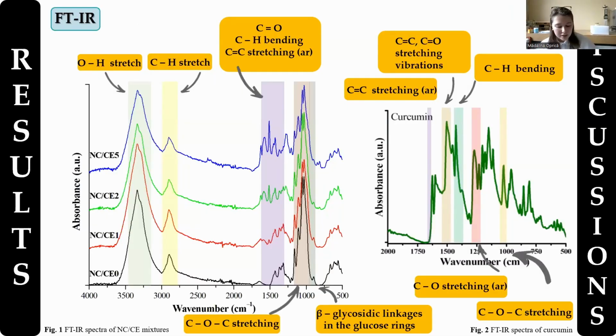The FTIR spectra presents the characteristic bands of nanocellulose, with the most important peaks at around 3,340 attributed to the hydroxyl groups abundant on the nanocellulosic surface, another at 2900 centimeters at -1 attributed to the carbon-hydrogen stretching vibrations, while another peak characteristic to nanocellulose is also at 859, which is attributed to the beta-glycosidic linkages in the pyranosic link of the glucosic unit.